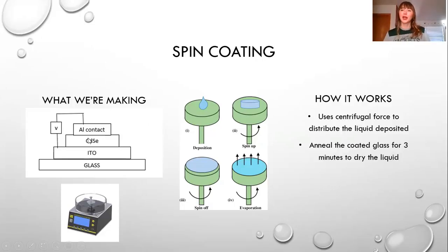So spin coating is kind of the same theory as a merry-go-round. You spin things really fast and they spread out. This image in the middle kind of shows how that works. We deposit our quantum dots in the middle, and then it spins and disperses them, ideally into an even layer. We had some trouble with that in our process, but I'll go over that later. So then we let that dry on some heat for a while, and our quantum dots are ready to actually be used as solar cells.